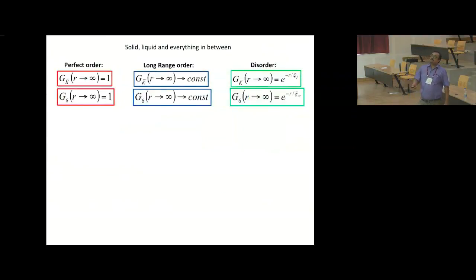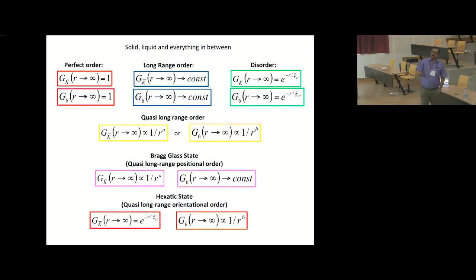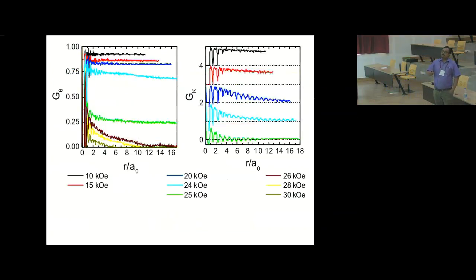Now, these two metrics allow you to get perfect order when at large distances both of these become 1. So perfect order you would possibly get only at T equal to 0, but what you get is long range order, where at large distances these go to an asymptotic value. And you can get a disordered state where both of these decay exponentially. But you can also get states that are in between, where one of these, positional or orientational order, can decay as a power law. So it will decay, but it has no characteristic length for the decay. So we try to see what they are for our system.